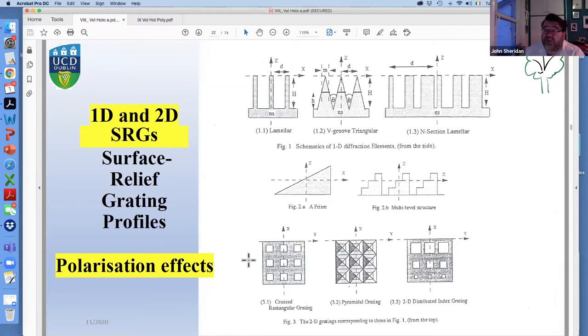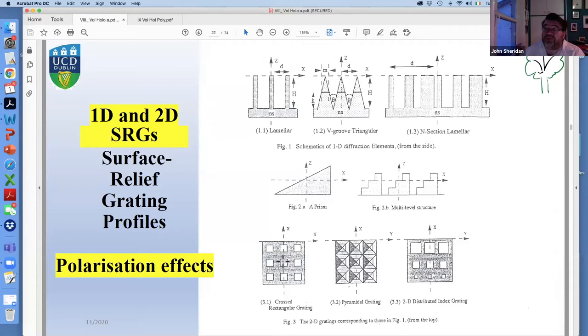In relation to polarization: if we have a two-dimensional structure and make it symmetric, both TE and TM will see the same pattern — no asymmetry — so we can effectively make the material polarization-insensitive, or certainly reduce polarization sensitivity. This goes for volume holograms as well — for example, crossed gratings where we'd have an interference pattern and then rotate the plate by 90 degrees and record again, producing deflections in two directions simultaneously, though we have to be careful to work with the Ewald sphere rather than the Ewald circle.